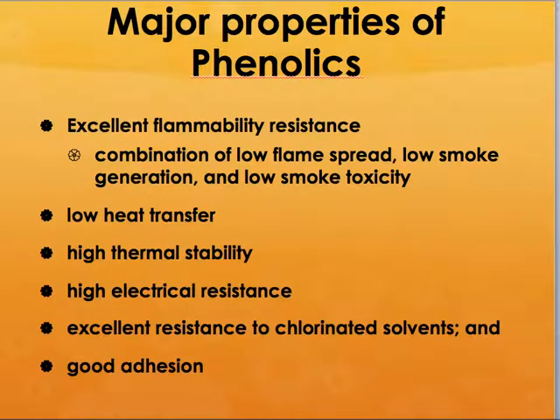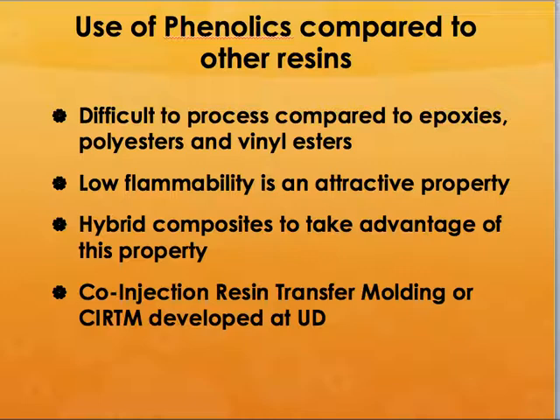Okay. So what are some of the major properties of phenolics? The first and foremost property is excellent flammability resistance, low heat transfer, high thermal stability, high electrical resistance. So you use them in junction boxes and things like that. And it also has fantastic resistance to chlorinated solvents. And it has very good adhesive properties, so you use that as an adhesive rather than as a composite resin matrix. But the problem with phenolic is that it is extremely difficult to process compared to epoxies. It has very high resin viscosity, so you can't easily infuse that into a fiber preform. So you have to use a pre-preg rather than an infusion type of process to make these composite systems where phenolic is the resin matrix.